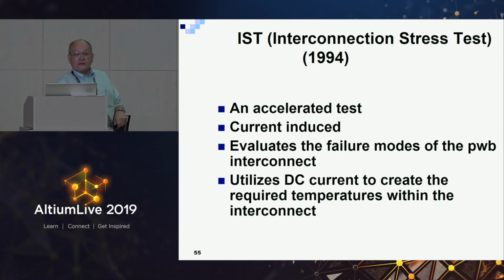IST is the other one, interconnect stress testing, in 1994. This is an accelerated test, but instead of using external heat, they pass high current through holes and heat the board up internally. A lot of people like to use it because it's quick and cheap. It's debatable whether or not it's simulating field failures, because the temperature is induced internally, and in field failures, the temperature extremes always come from external. And this one is internal, and it cannot go below room temperature. And the whole negative transition creates all different kinds of stress activities that this can't test for. So there's a lot of debate about this.